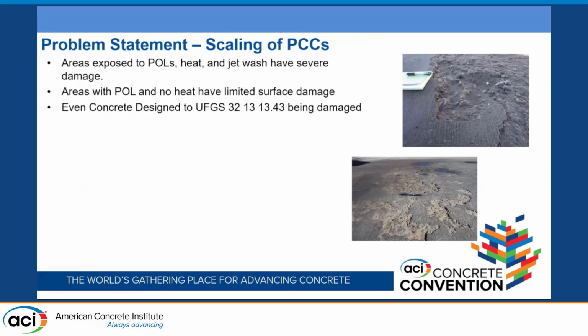So, the scaling of Portland cement concrete. The areas exposed to POLs, petroleum, oils, lubricants, and jet wash can see severe damage that expedites the process of the Air Force having to come in and replace it and do repairs. And even concrete designed to the high heat UFGS, the Tri-Services standard that we do airfield pavements on, even the high heat version sees damage from these aircraft.